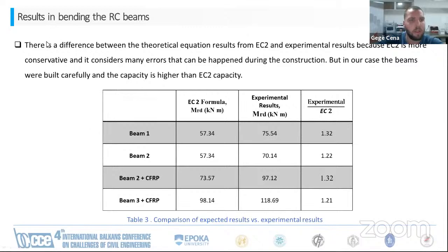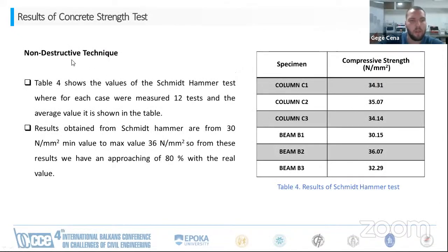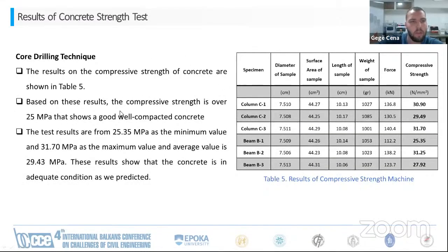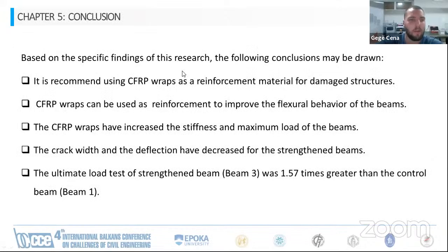Also, we got the results in the bending of these reinforcements, the experimental bending. And we got the results of non-destructive techniques that show that the quality of concrete was from 30 to 36 megapascals. These are the results of the core drilling techniques. Because it is a cylindrical sample, we got 25 megapascals, which is also the C25/30 grade. And after all the experiments, we got the conclusion.